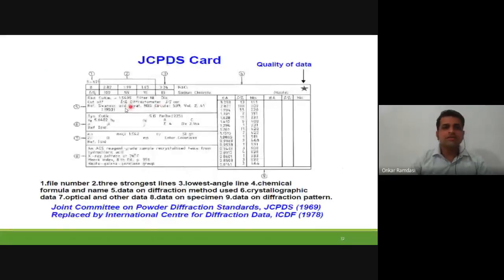Then these are the parameters: the radiation source which we are using, that is copper K alpha, having wavelength 1.54 angstrom. Then a nickel filter is used, and the cutoff wavelength is there. And these are the references, the 5 number reference from which they have taken this data, which is Swanson, Fuyat, NBS Circular. This was the reference journal from which they got this data. Now the structure symmetry is cubic, Fm3m was the space group. And these are the lattice parameters a, b, c. In this case, they have just mentioned a. This is the density. Then the 7th parameter is the optical and other data.